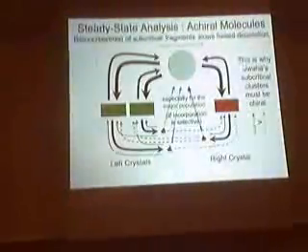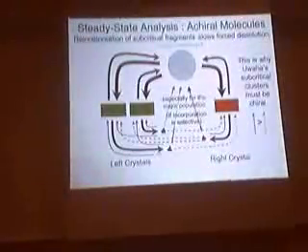The reason dissolution is very fast is because the solvent is undersaturated, so not much comes back on, right? But once you build up concentrations, if you have lots and lots of solvent, everything will dissolve rapidly and nothing will come back on. But if the solvent is limited, then at a certain point the number going off matches the number coming on. And that's what happens in steady state.